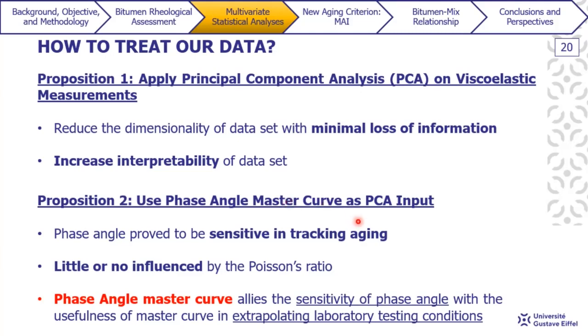So phase angle proved to be sensitive enough to track the aging variation between different aging levels. And also, unlike the models, bitumen phase angle seems to be little or not influenced by the Poisson's ratio.